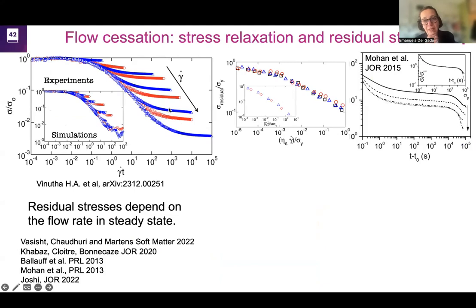And these are experiments that have been performed in several groups over the last years. This is a recent one from a group where I've been involved in the work, and the experiments have been done in the group of Veronique Trappe at the University of Fribourg, together with Marco Caggioni of Procter & Gamble. This is a model jammed soft solid that they have forced to flow, so it has this Herschel-Bulkley type of rheological behavior. Now you stop at different points, at different rates, while the system is flowing, and you measure your stress relaxation.